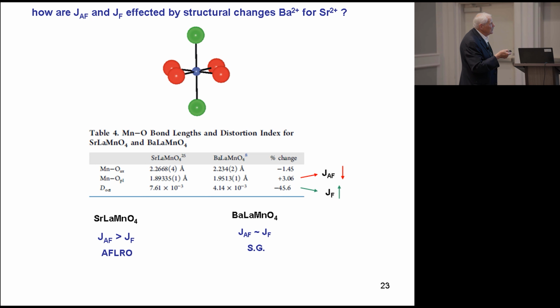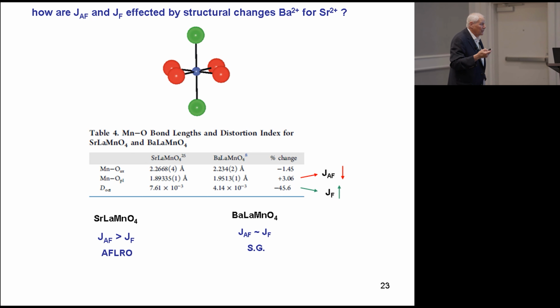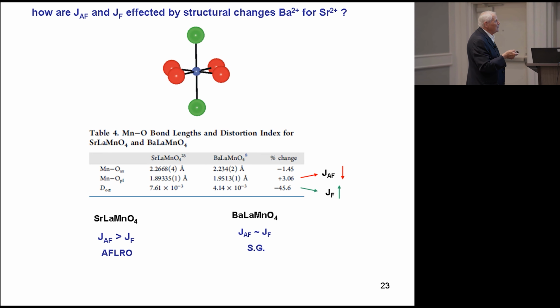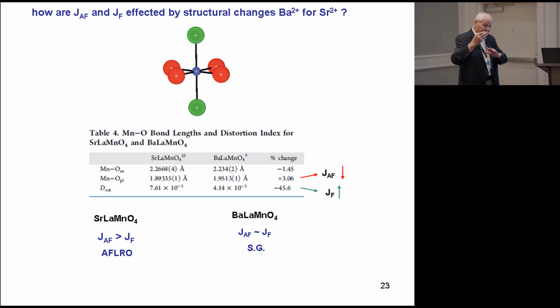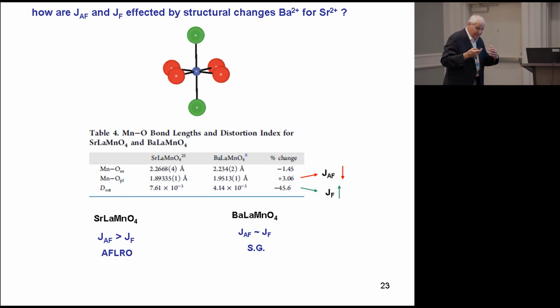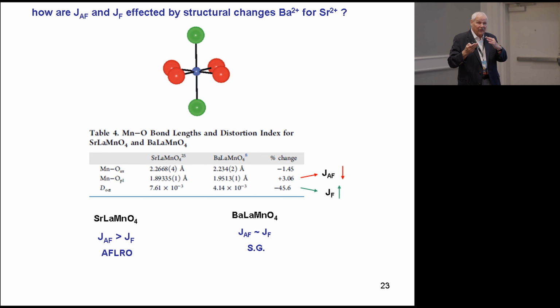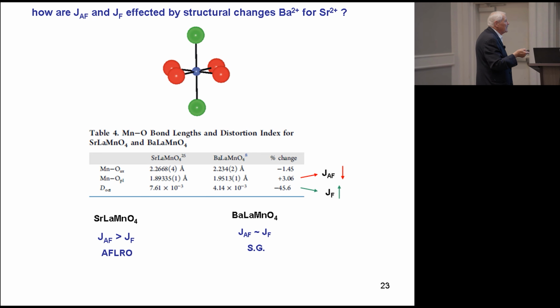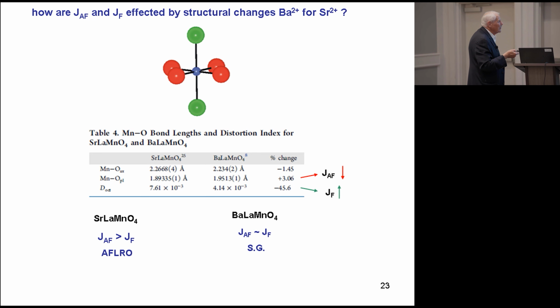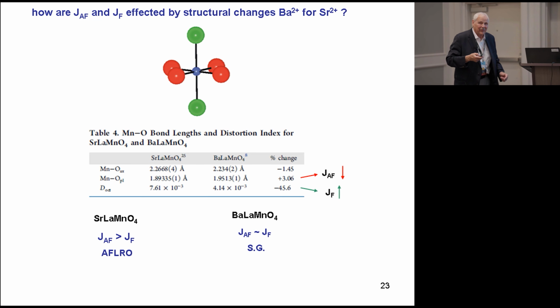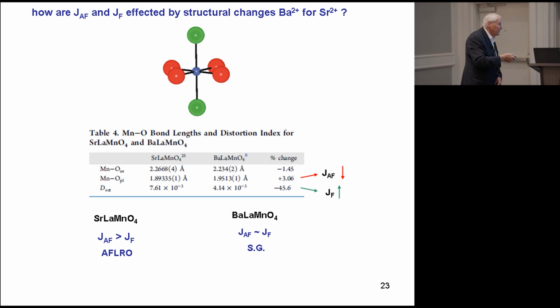And just to remind you what happens here, you can estimate the critical temperature for a two-dimensional system. And there are two components. One is the one you might expect, which is the exchange interaction between the layers. There's also the 2D spin correlations. And so if you can kill off the 2D spin correlations, you will essentially kill off the magnetism. And this is supported, this is not just a bunch of diagrams that I produced, this is supported by some DFT work.